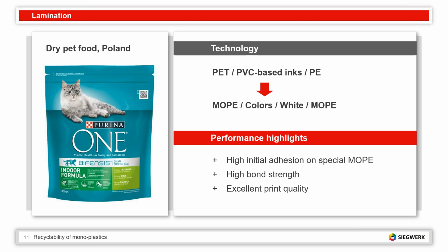And there our customer, together with us, moved the structure from a PET PE laminate, which contained PVC-based inks. So this is basically the worst case for mechanical recycling. We moved this together to MOPE laminate with colors in white in between.